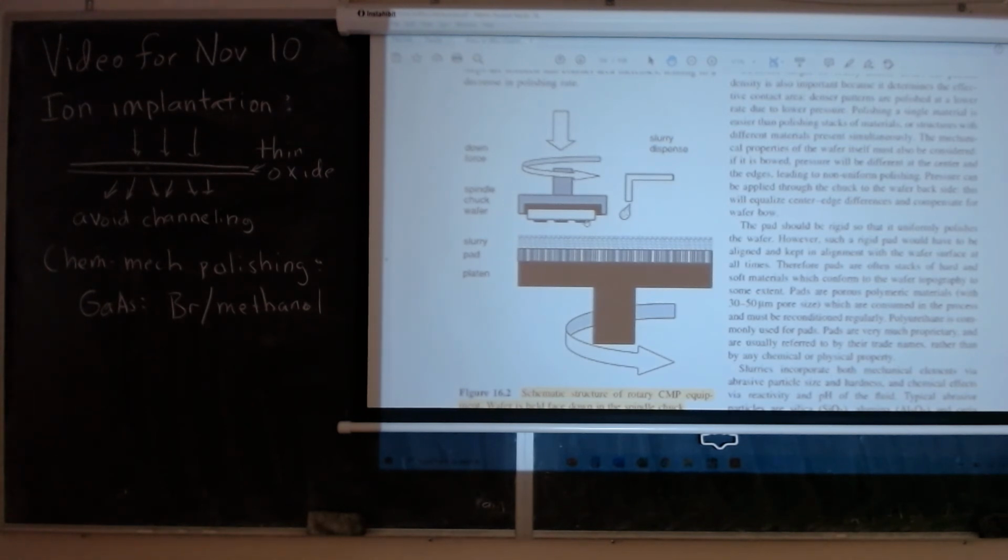And now, as part of my career, I've done certain polishing for different reasons than usual. And what I can tell you is that if you're using a slurry, it's basically rate versus finish, in the sense that if you use larger slurry particles, you'll go faster, and again, that's sort of more like grinding. Whereas if you go to finer slurries with smaller particles, your rate of removal of material will go much slower, but you'll get a nice finer finish.